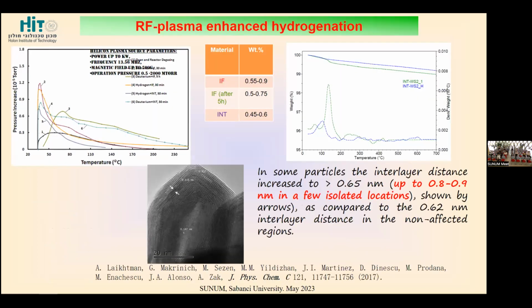And finally, it was a task to prove that this type of hydrogenation indeed produces some hydrogen inside. So we first measured, by some normalized way, the desorption of hydrogen in situ, inside the plasma reactor, when we exposed the samples to hydrogen. Then we heated the samples and we proved that only hydrogen can be released. We also did these experiments with deuterium to be sure that this hydrogen comes from our processes and not from somewhere else. It was also confirmed by TGA.